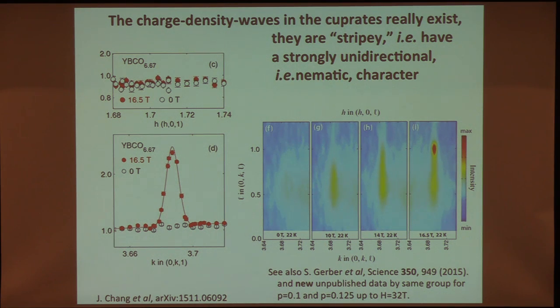My colleagues at SLAC have, and this is unpublished two-week-old data that nobody else in the world knows about, so you're among the first people to hear about it, shown that this same sort of structure persists up to the highest fields they can reach in the pulsed field experiment, which is 32 Tesla. So this is over a broad range of fields, and also now over a range of doping. At this lower doping, the critical field is 23 Tesla, so inaccessible to static field measurements. So this is really a feature of a regime of the phase diagram.